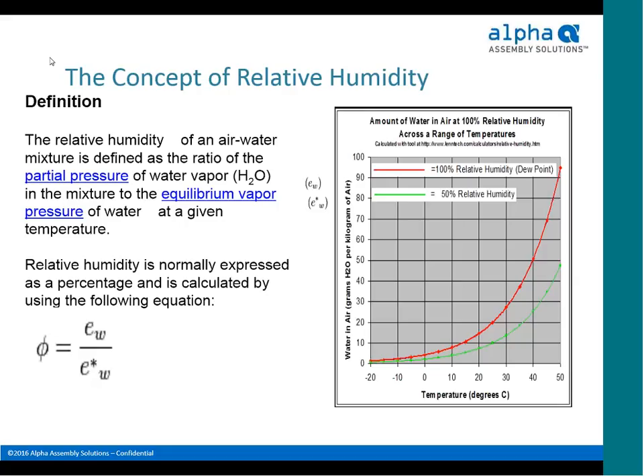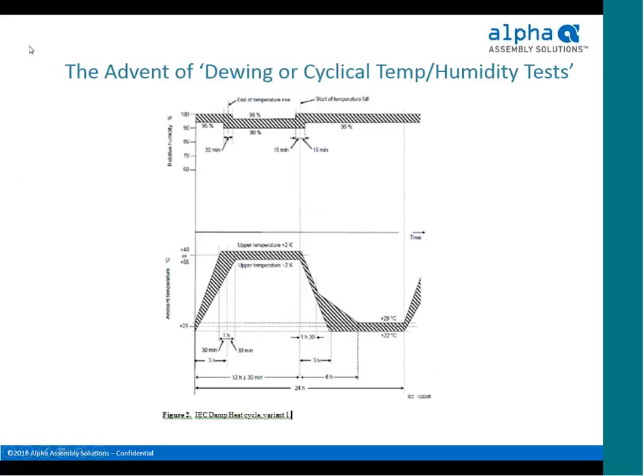So in testing and running these tests, you both have to cycle the temperature. We've also got to have a way to control the amount of moisture in the air, especially as the test conditions get cooler, because if you don't pull the moisture out, you'll get the chamber temperature below the dew point, then you'll get condensation and it can ruin the test. So test chamber development and definition is very important. It's really difficult to do, apparently.